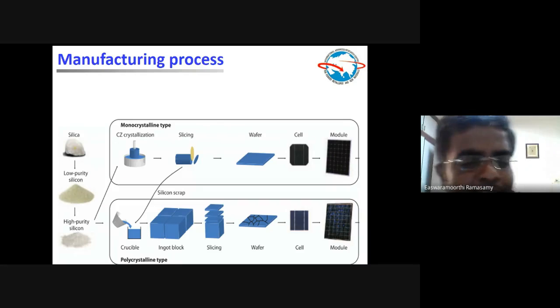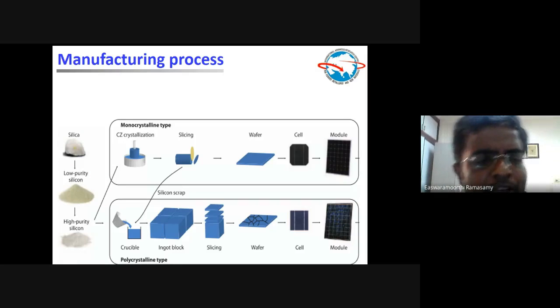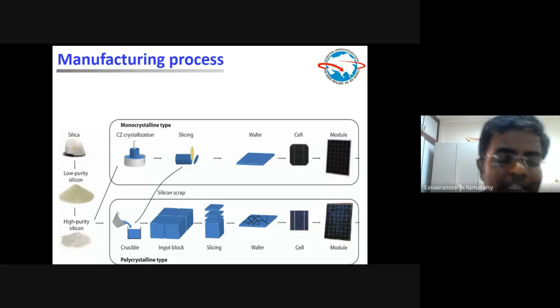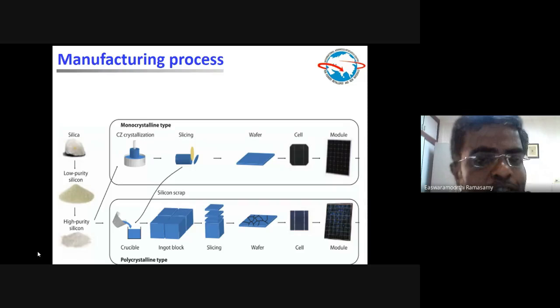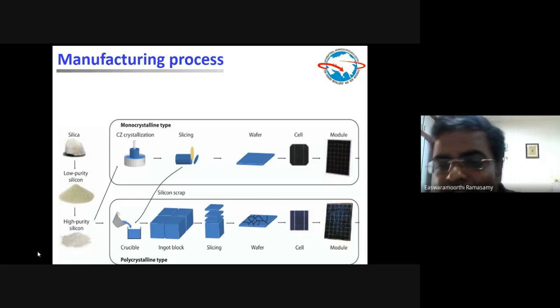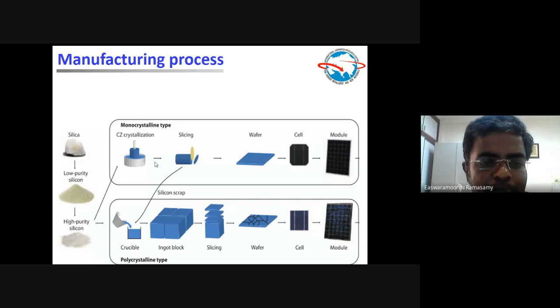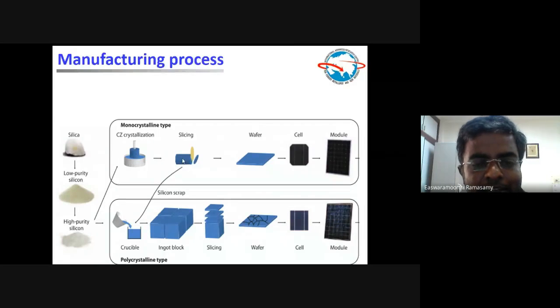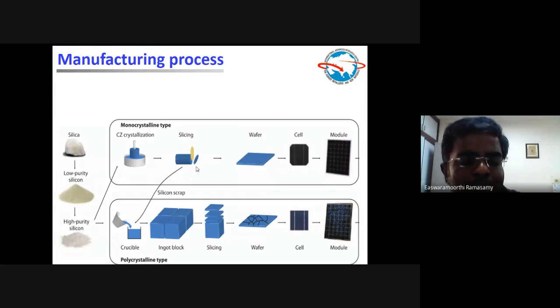So the cost of this high purity silicon is much higher than the low purity silicon. So in this way, the cost of the material is going up. Once you have high purity silicon, it can be melted, and then you can grow these monocrystalline ingots. That is called single crystalline silicon solar cells. As shown in this top panel, you get a seed and then grow, and this is a single crystal ingot. The ingot means it's kind of a tubular structure of silicon.